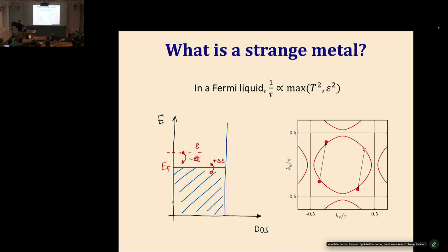So a quasi-particle can scatter off another quasi-particle close to the Fermi energy. So this one might scatter to here to conserve momentum. There's some filled state that would have to scatter to an empty state over here. The initial quasi-particle would lose some amount of energy. The scattered particle would gain the same amount of energy. And you have to integrate both over this energy transfer and over the initial energy of the scattered particle. Two integrals over energy would give you epsilon squared. So it's as simple as that.